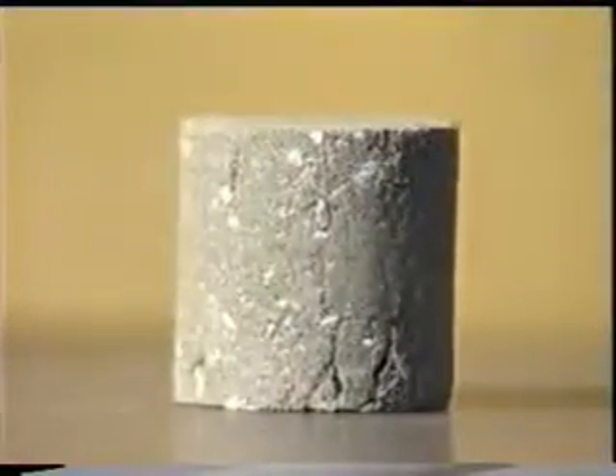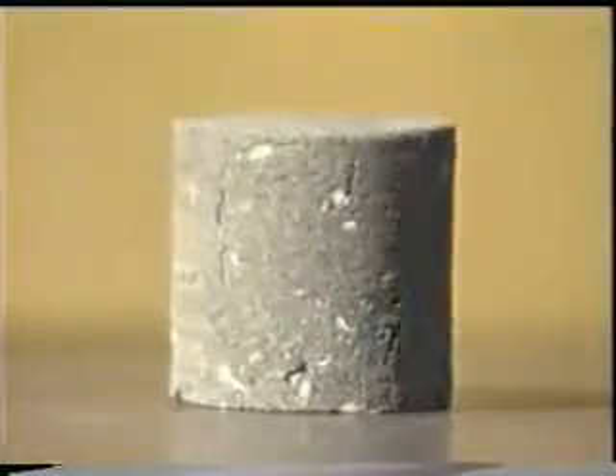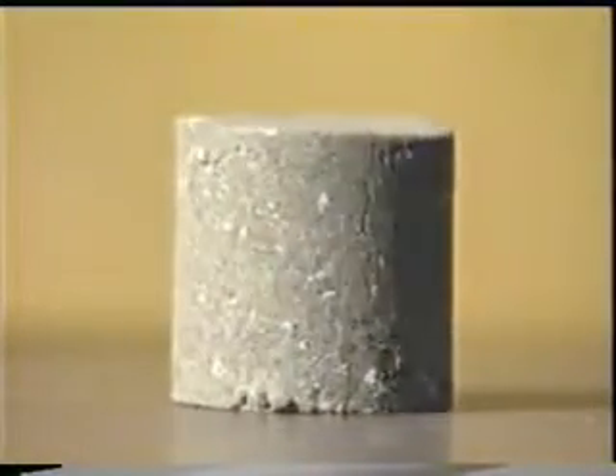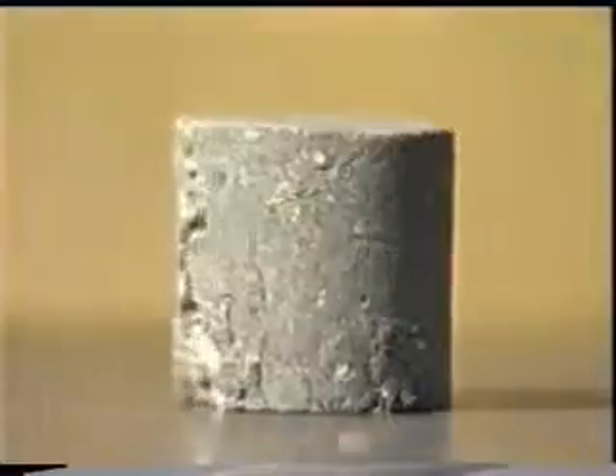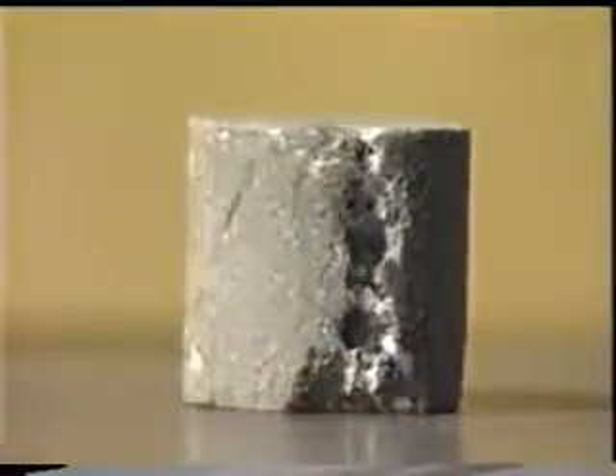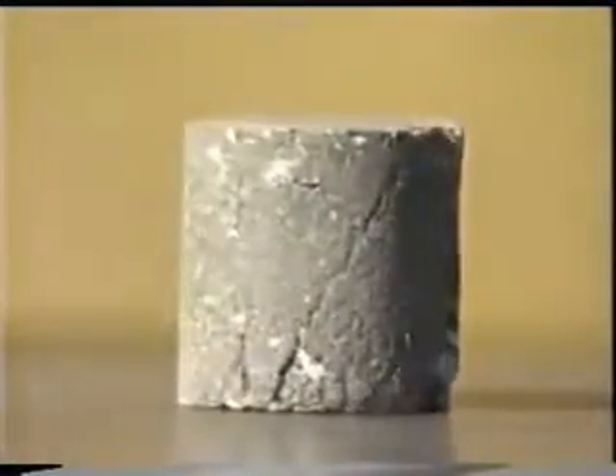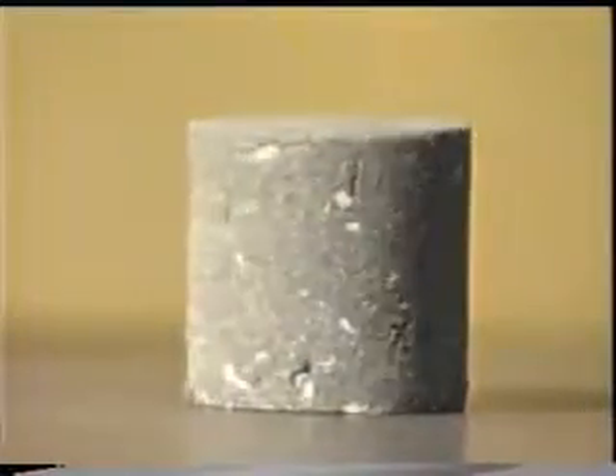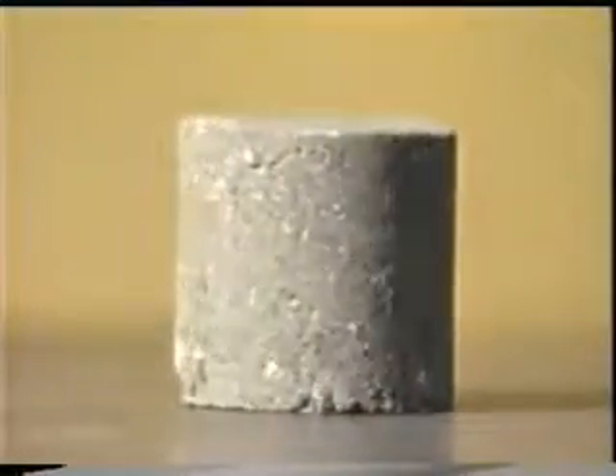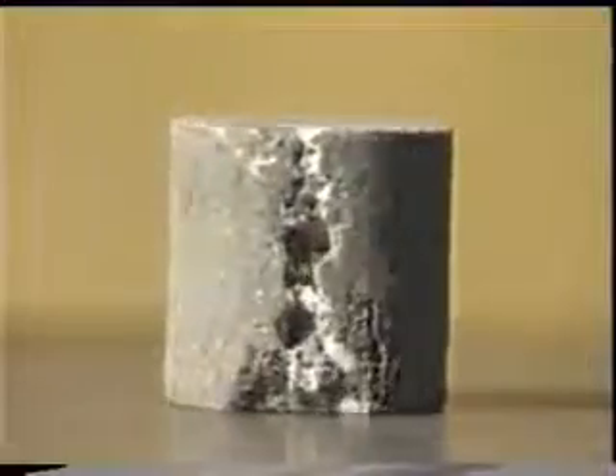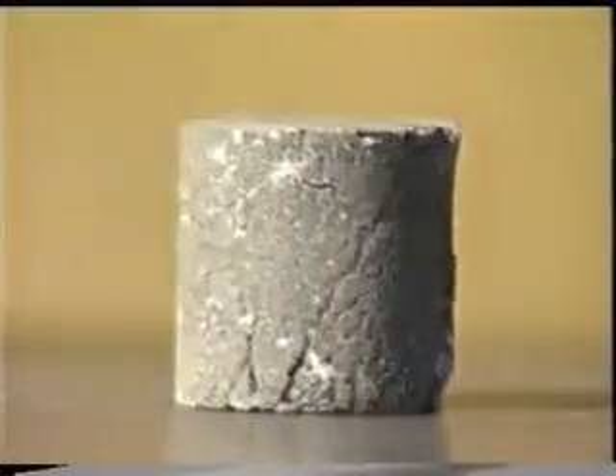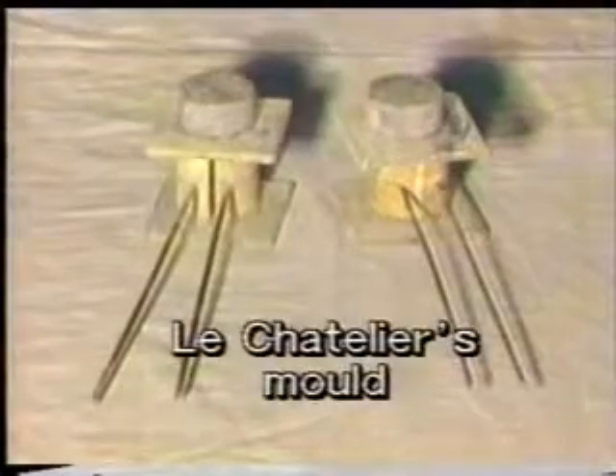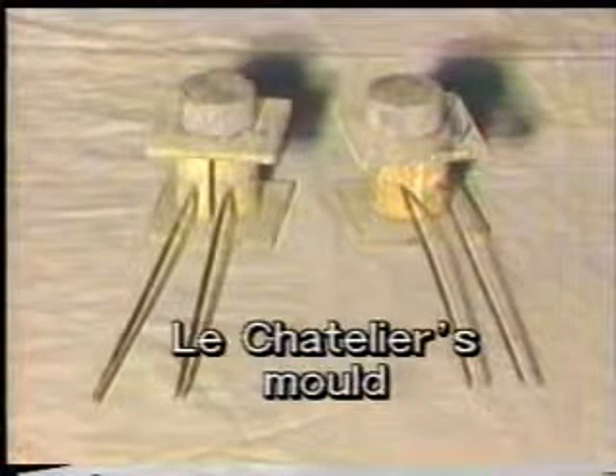In cement, cracks are developed due to the presence of free lime and magnesia, which slakes slowly in the presence of water and increases manifold in volume. The test of soundness is conducted with the help of Le Chatelier's mould.